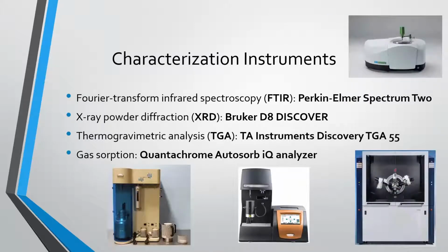After we created our samples, we had to then characterize to be able to tell what we made. For our first characterization steps, we used FTIR and X-ray diffraction in order to verify that the product was made in a similar, or we had a similar ending product as the traditional method. FTIR and XRD allowed for structural analysis and for us to observe the bonds. We then used thermogravimetric analysis, or TGA, to find impurities such as water of hydration and byproducts such as acetic acid, and to observe the thermodynamic stability, which is incredibly important for copper BTC since it would be used in various different applications over wide varieties of temperatures. We then looked at the gas absorption for both surface area and pore sizes to ensure that our created MOFs were similar to the ones created in the traditional method.